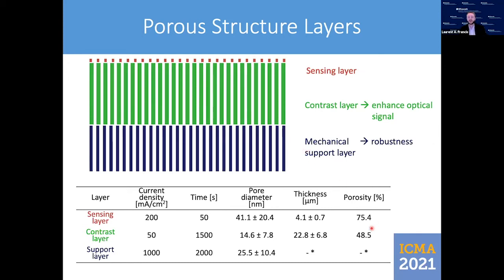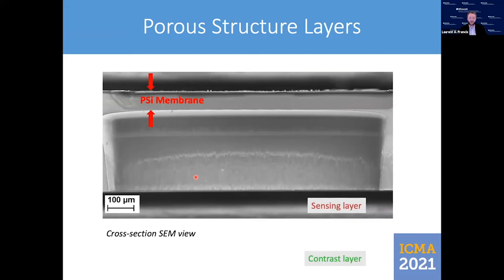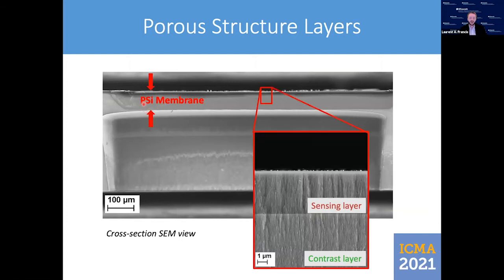The porosity is different, and this is very important. The porosity of the sensing layer is very important and quite huge. The contrast layer and the support layer have different porosity, only to allow the flow through of the liquid. If we take a close look at the membrane, we see that it's less than 100 micron thick. This is a cross-section view. And we can also zoom in on the sensing layer, where we see the interface with the contrast layer here.